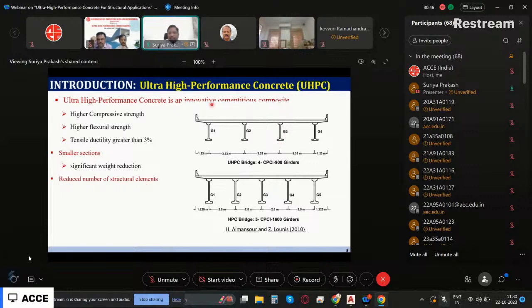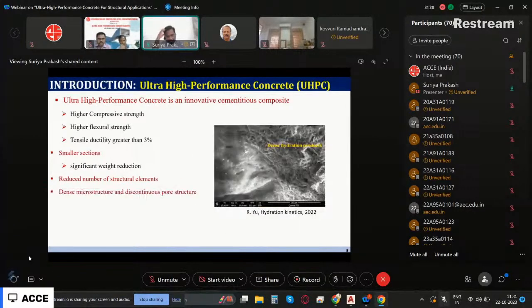The same goes for the superstructure. With regular concrete, I need to put a spacing of 2.5 meters here. With the high performance concrete, I can go for 3.3 meters. So even the number of girders required: in this case you see 5 are required and the depth is also high, and here I need only 4 girders for the same carriageway width. So I end up with fewer structural elements. That's what we talked about in the case of the Hyderabad metro example, right?